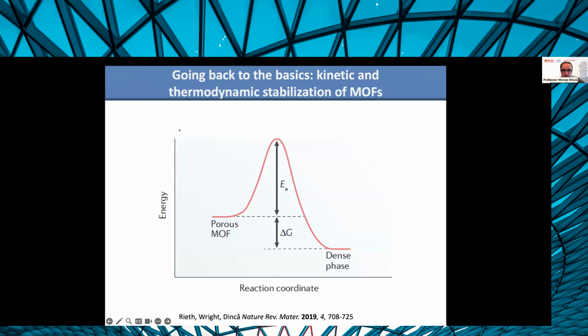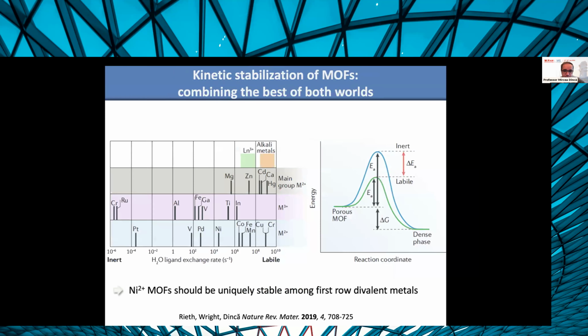And what we need to realize really is that MOFs, all MOFs, are actually metastable materials, just like any other porous material. There is always going to be a dense phase that is going to be much more stable, or at least somewhat more stable than the porous phase. So all MOFs are metastable materials. There's nothing wrong with metastable materials. They can be very metastable, if you will, because they then have a very large activation energy to going to that undesired dense phase. In other words, we can make MOFs very kinetically stable. And those MOFs that are actually stable to water, or are known to be stable to water, are kinetically stable to water.